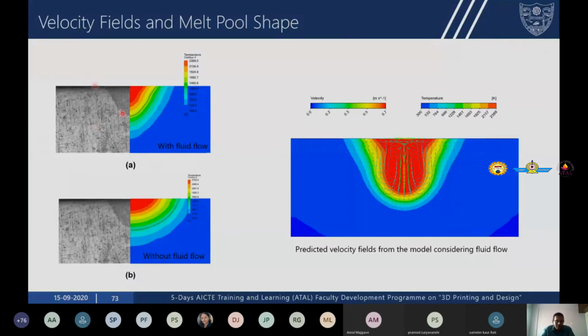Here is the prediction of the shape of the molten pool with the fluid flow and without the fluid flow. On the left side is the macrograph obtained from the optical microscope. On the right side are the simulation results. You can clearly see that when you consider fluid flow, the prediction of molten pool shape is much closer compared to the case when you don't consider fluid flow. You are seeing a different molten pool shape. So the importance of considering fluid flow when doing simulations of laser additive manufacturing becomes clear.